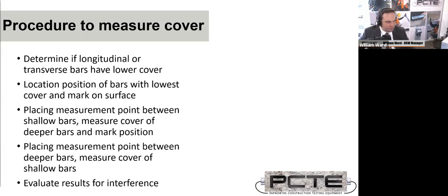Note, if you have your reinforcing bars too close together, so you've got more than one reinforcing bar in the electromagnetic field of the cover meter, that would be an apparently thinner cover. So let me continue with the procedure. First, the operator just quickly checks to find if the longitudinal or transverse bars, or horizontal or vertical bars, are closer to the operator. And then the bar that is closest to the surface, the lowest cover, we scan over that and we mark its position a couple of times.